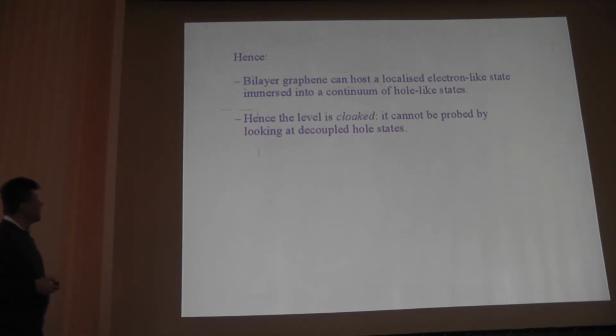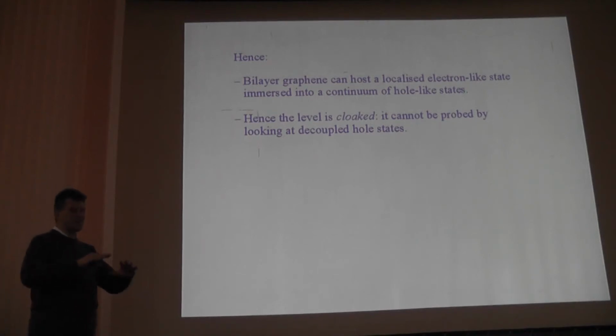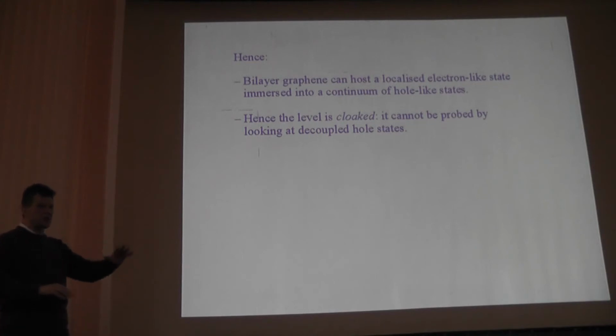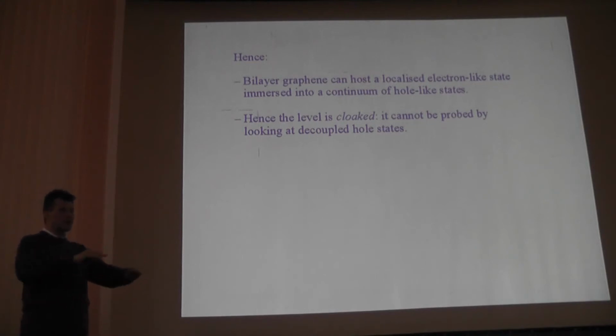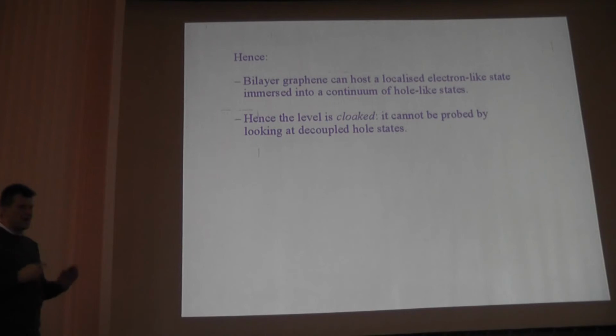but the implication is that this state in graphene is in fact an invisible state. So you have a hole continuum, and you have a discrete electron level immersed into the hole continuum. Holes go around, they don't scatter into the state, they don't see if the state is occupied or not, for example. So in some sense, that's similar to the invisibility that Ulf was talking about.